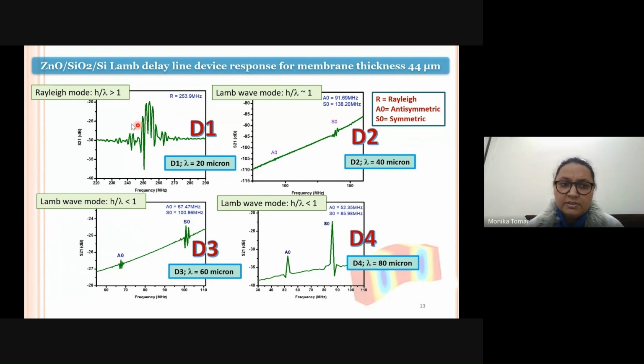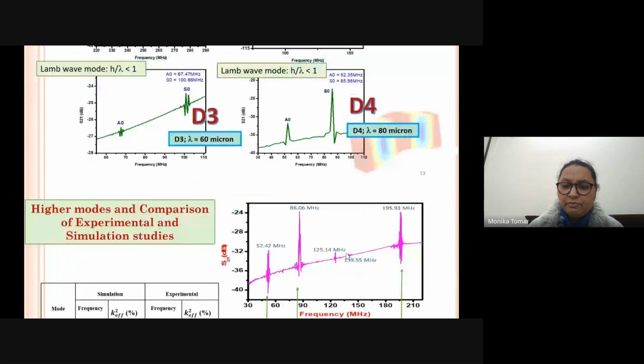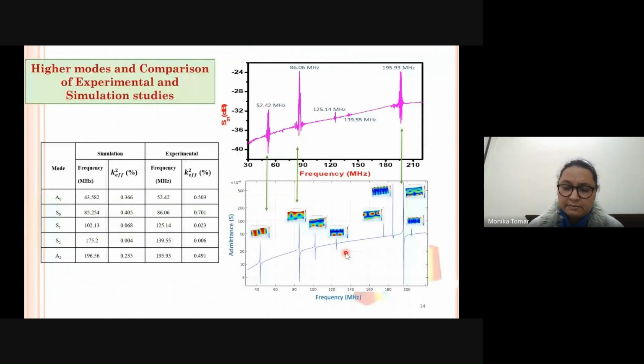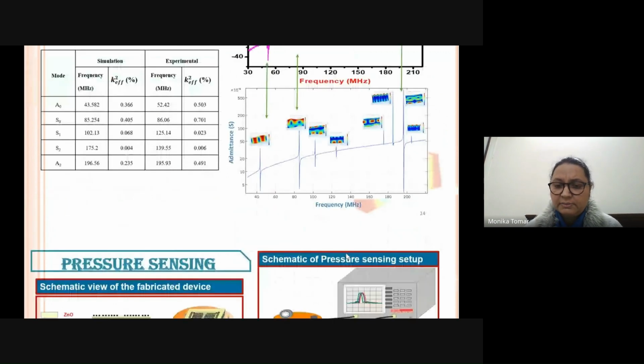H is very high, so the H by lambda is very high, and we do not get any Lamb wave mode. But for the other devices, when the H by lambda becomes approximately equal to 1, or when it becomes much less than 1, then we get very good Lamb wave modes. So these were matched with the theoretically obtained results, and we want 100% matching.